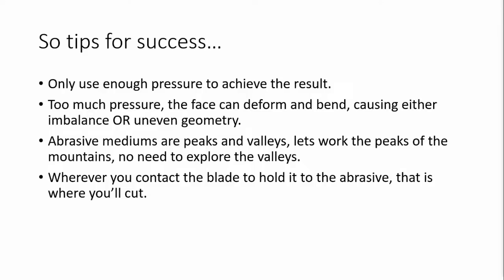And the last thing that's important that I think gets neglected is that wherever you contact the blade to hold it to the abrasive, that's where you'll cut. If your finger pressure is closer to the top of the primary edge where it meets the secondary edge, you're probably going to be grinding more behind that edge. If you contact just at the edge, you're going to grind there. So being conscious of where you're touching your blade is going to be important, because that's going to tell you a lot about how you're forming your edges and why you might be seeing certain things in your sharpening that you otherwise didn't quite think about.